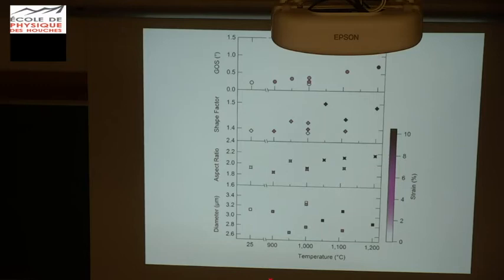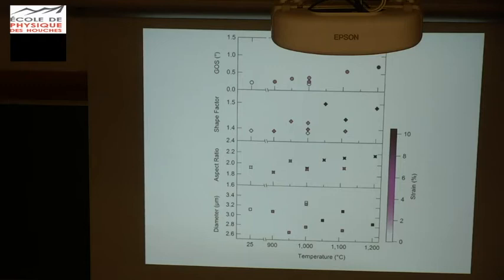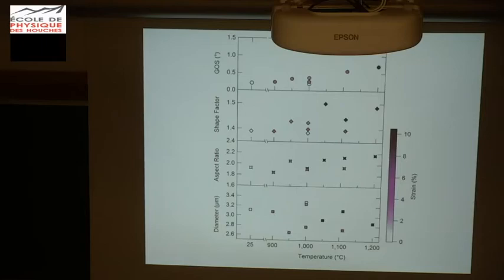We went back for some extra statistics from MTEX. As a function of temperature, there is basically no drastic change in grain size, no drastic change in aspect ratio — from 1.8 to 2.0 — so nothing drastic in the shape factor. The only little pop-up in these experiments is grain orientation spread, expressed in angle. As soon as you have a little bit of high temperature kicking into the system, the grain orientation spread increases a little bit — and we've seen that also from the misorientation maps.